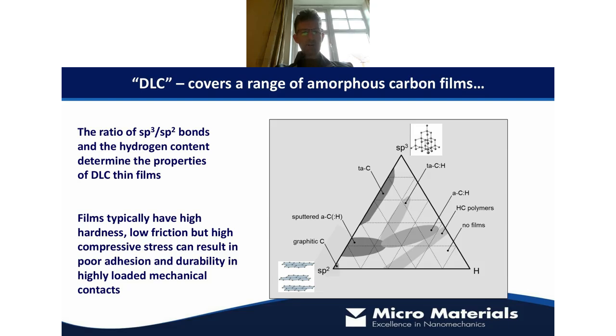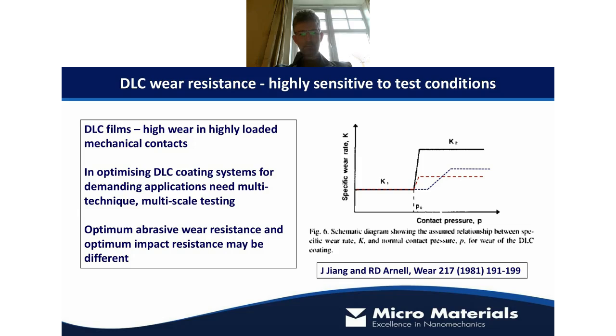And what is very attractive to these systems is that they can be deposited with high hardness and low friction, but typically with relatively high compressive stresses, which can be partially beneficial, but equally can be responsible for poor adhesion and durability in highly loaded contact. So we were interested in studying this, and this has been known for some time.